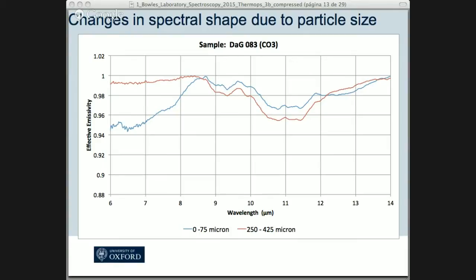So here you can see this characteristic roll-off at short wave, which is very diagnostic of small particle sizes, and this reduction in spectral contrast. So immediately, if we saw a spectrum like this when we went to an airless body at moderate resolution, maybe with a spacecraft, it would tell you instantly that you've got something going on with the particle size fraction. This could be very useful for comparison with, say, thermal model output.